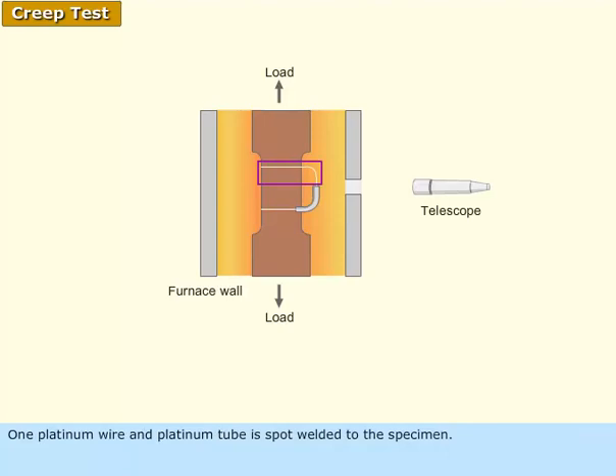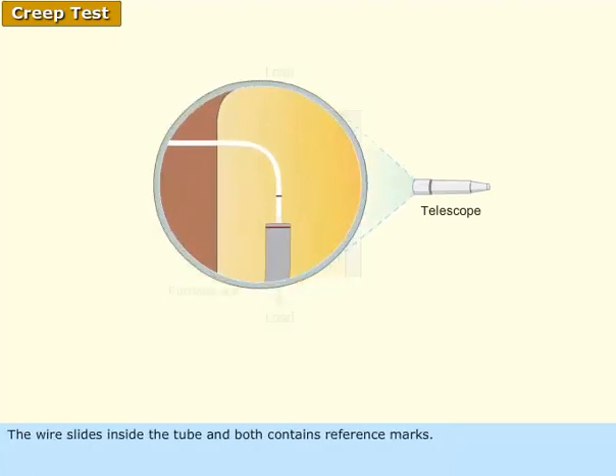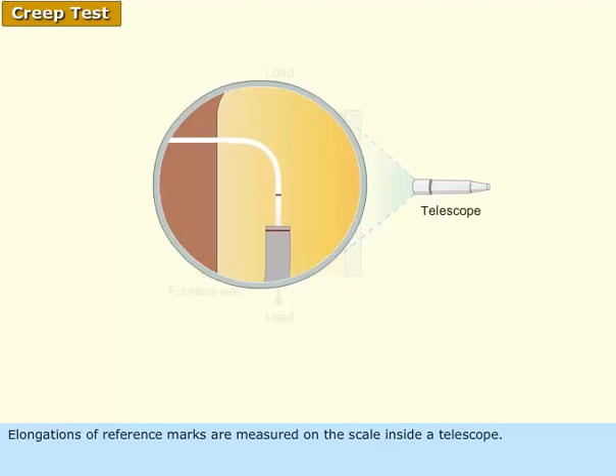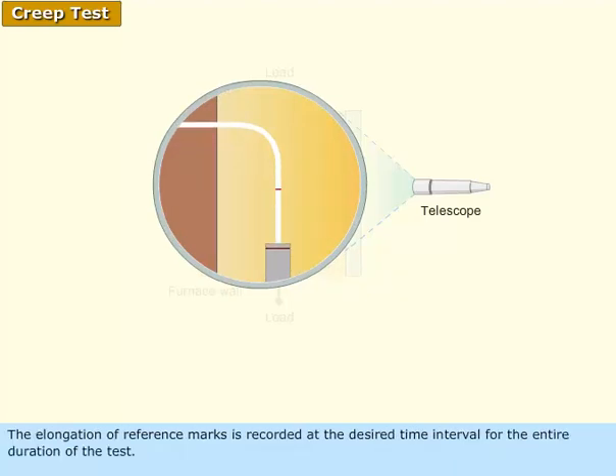One platinum wire and one platinum tube are spot welded to the specimen. The wire slides inside the tube and both contain reference marks. Elongation of the reference marks is measured on the scale inside a telescope. The elongation of the reference marks is recorded at the desired time interval for the entire duration of the test.